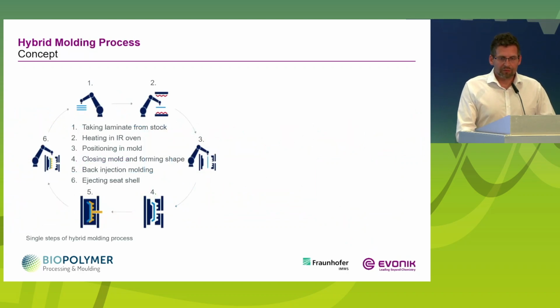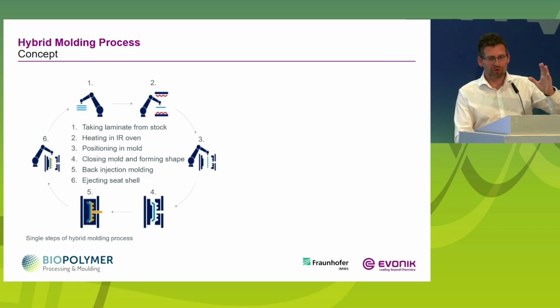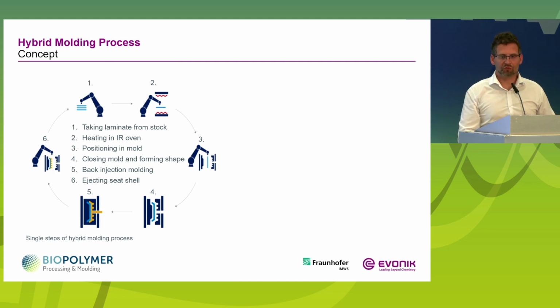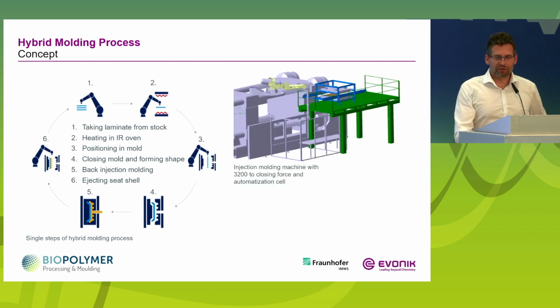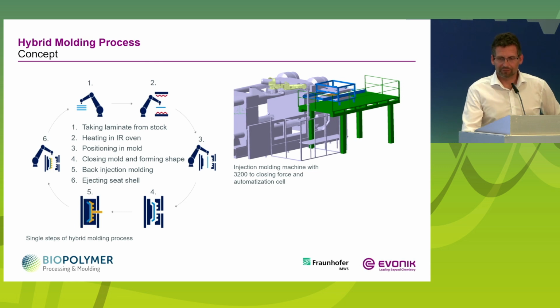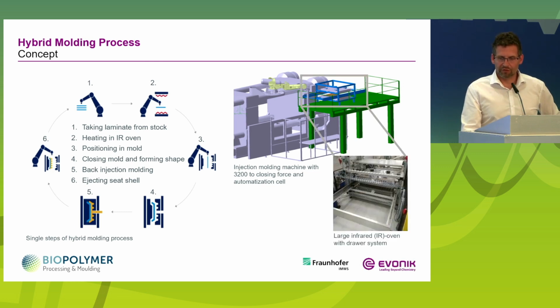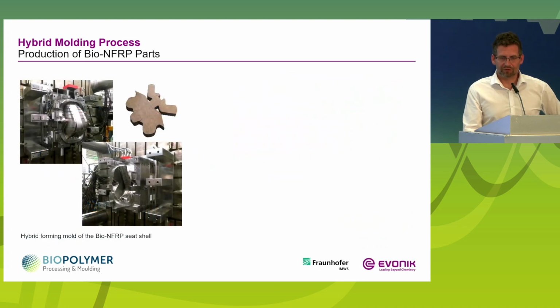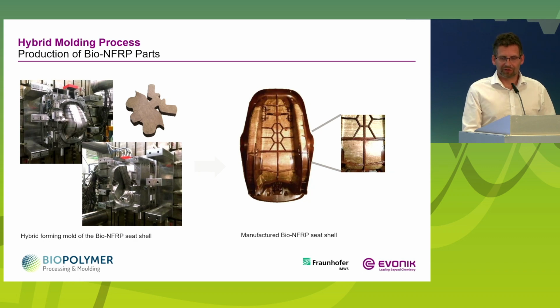Yeah, from the process, the hybrid molding process, in the first step, we take the laminate from the stock, heat it up in an IR oven, then position it into the mold, close the mold, and then the shape is formed. During back injection molding, the full form will be molded, and then we have the possibility to eject the seat shell. Yeah, this is the machinery, and on top this IR oven, which we used for producing this demonstrator. And here you have an insight into this mold where we produced this seat shell, and this is the final product at the end.